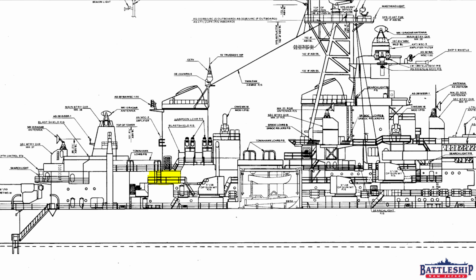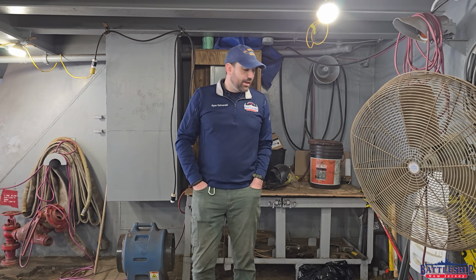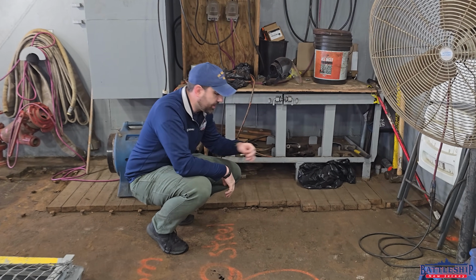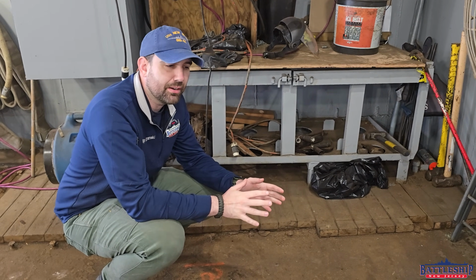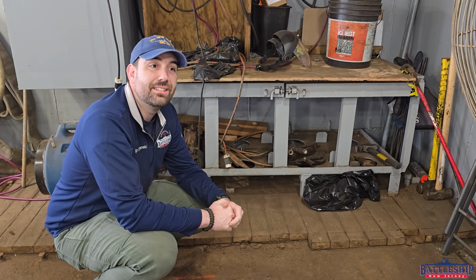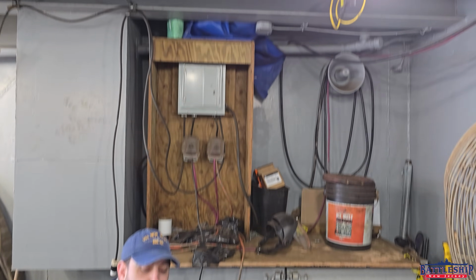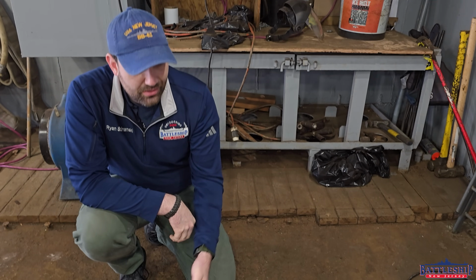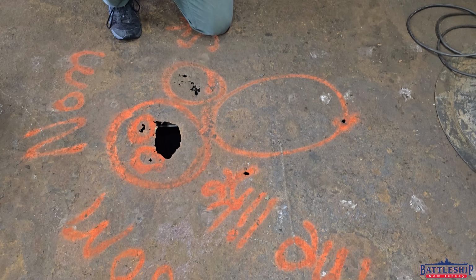So we are up here on the O2 level on the port side. This is one of the positions where a 5-inch gun was removed so that the overhead could be put in for the missile deck. When that was done, the Navy did not replace the original teak wood up here with new teak wood. They didn't even replace it with the laminate that they used elsewhere on the ship. They replaced it with straight Douglas fir. And it's kind of okay in here. The wood itself was in relatively good condition because it's protected by the overhanging missile deck. However, the steel underneath was not in good shape.